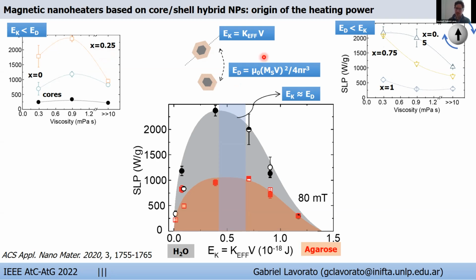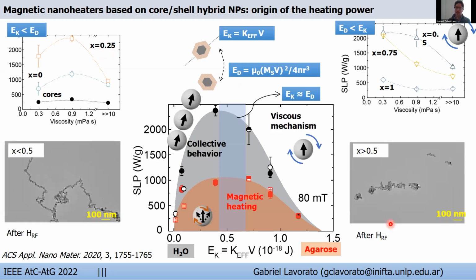And to check this hypothesis, we looked at the arrangement of the nanoparticles placed in the microscope immediately after the application of the field, and we found that one-dimensional chains are much more likely to be observed for samples with lower anisotropies. So 3 regions can be clearly identified according to the anisotropy, the size, and the medium: a collective behavior zone, a viscous mechanism, and a purely magnetic or Néel heating for immobilized particles. So hopefully this general picture could be useful as a guide to design core shell particles with large heating rates while meeting the limitations of different applications.